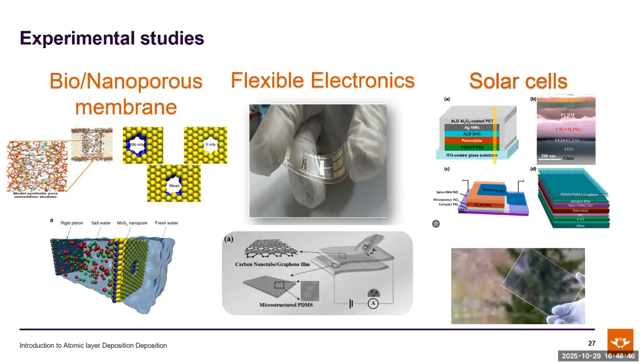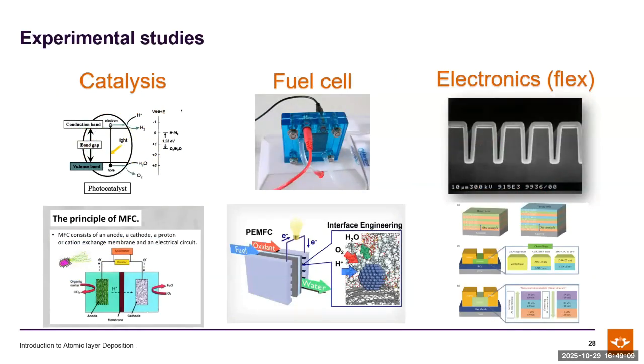But anyway, it's a transparent solar cell, and we are still trying to get better results, because if you can have a transparent solar cell with performance similar to a typical solar cell, then you will have a huge market for that. It's not easy to develop. Then the catalysis. We are good at ALD and can develop the catalyst very easily for deposit on the surface you want. And fuel cells, PEM fuel cell and electrolyzer, and then we also use this to develop for hydrogen generation.